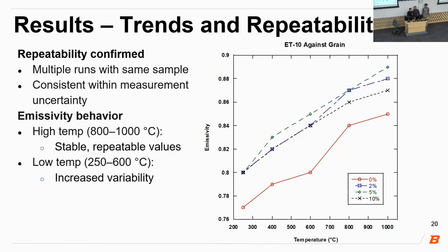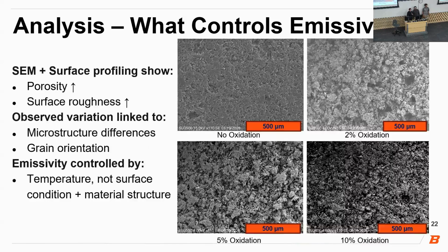At the start of the data collection, we ran one sample 3 times through, and we saw consistent data across all 3 runs, meaning we had very good repeatability that was within our uncertainty. All samples follow the same overall trend. Emissivity increases steadily with temperature from 250 up to 1,000 degrees Celsius.